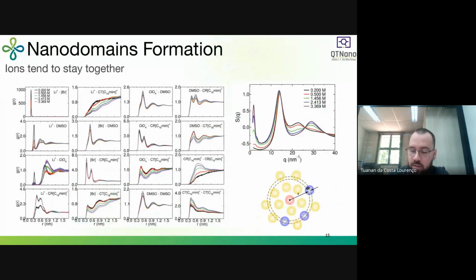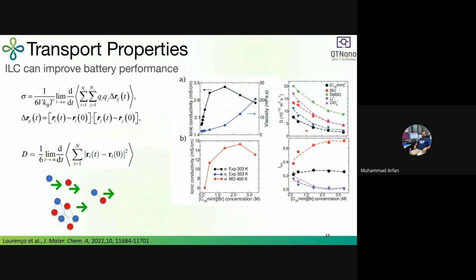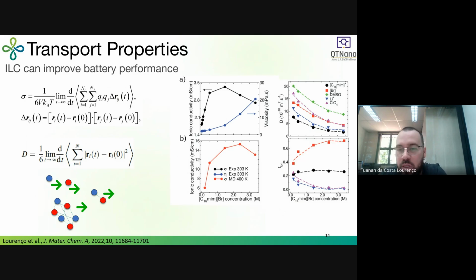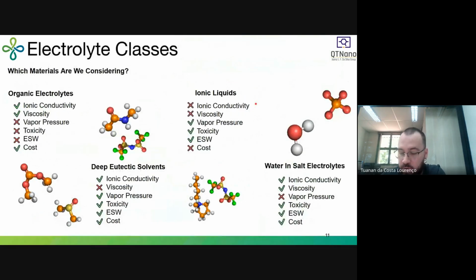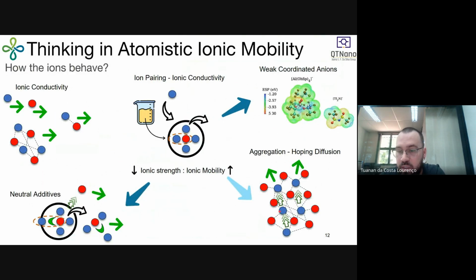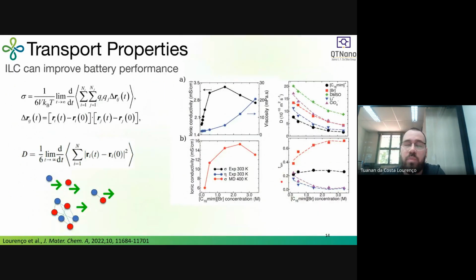If you have a large aggregation, you are going to see high viscosity, because with more and more ions you have lower and lower ionic mobility. So with aggregation, in general, you are going to see a decrease in the ionic conductivity. However, if you have aggregation and easier movement of the ions within the aggregation, you are going to see a bigger contribution of the ion to the ionic conductivity.